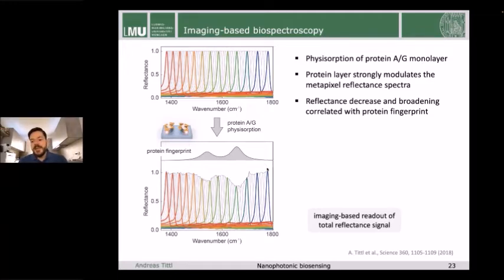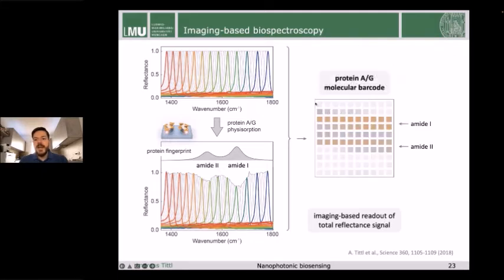However, the advantage of this imaging-based method is that we can actually read out the total reflectance signal. So we come in with broadband illumination, we take an image of this pixelated metasurface, and then we just look at the total reflectance signal. And this allows us to get an imaging-based representation of the molecular information in the sample. So you can clearly see the amide I and amide II bands here as high-intensity regions of this image, which we call a molecular barcode of the protein A/G.